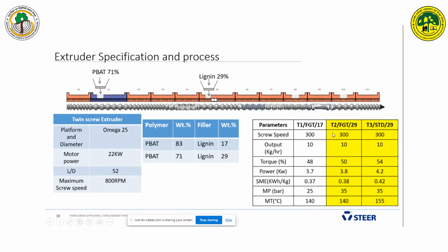and if you compare the FGT technology and standard, there is a difference here. The standard is giving a little bit higher torque, but the power consumption is also higher, and the specific mechanical energy is higher. And the melt temperature is almost 15 degrees better in FGT technology compared to standard technology.